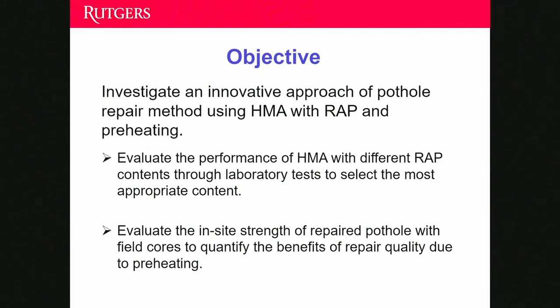Therefore, in this study, we are trying to see if we can add some recycled material to the asphalt patch, and then achieve some environmental benefits. But certainly, RAP material has some durability issues and might be very sensitive to moisture. So we will still introduce the preheating method here, and we want to see, with the combination of RAP and preheating, whether we can achieve environmental benefits without significantly impacting the performance of the patch.